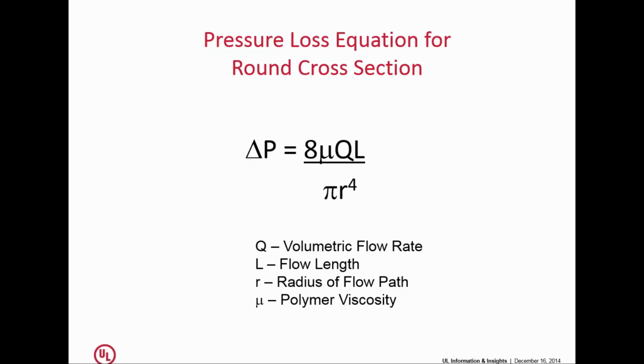L is the length of the flow path. This is pretty much governed by the size and shape of the part and where you chose to put the gate or gates. The longest distance you have to cover from the time the material enters the mold to the time it reaches the end of the cavity is your limiting factor for your flow length. And then in the denominator, we have this factor, and this is basically the diameter of your flow path. If it's round, or if it's rectangular, this would be AB cubed, where A would be the width and B would be the thickness. But essentially, it's the geometry of the path through which the material is flowing.